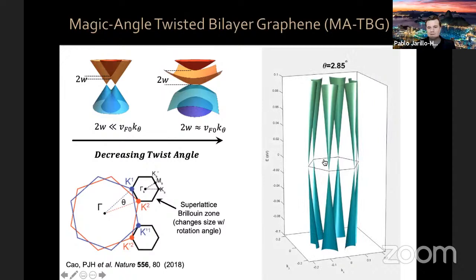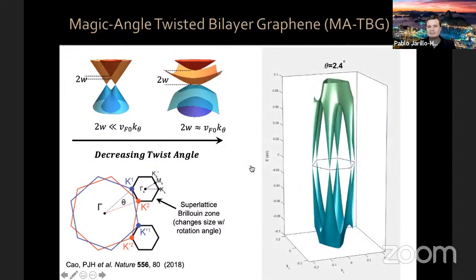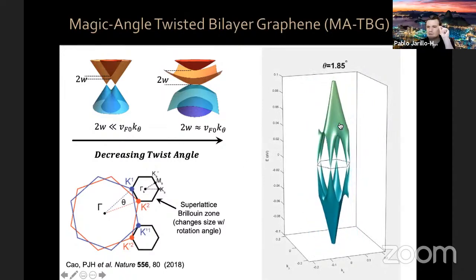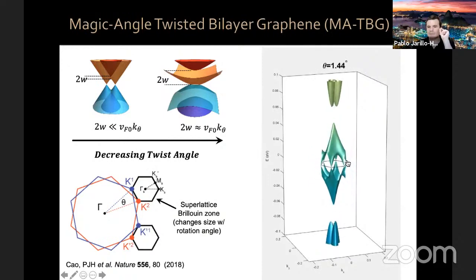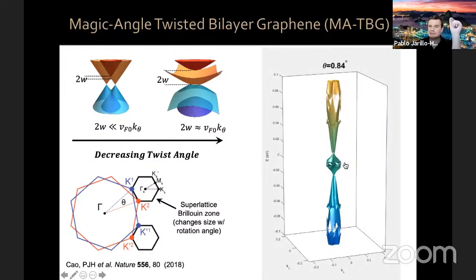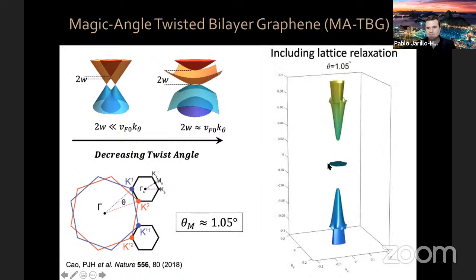So I'm going to run it again. As you can see, there is a particular sort of singular behavior. The band becomes extremely flat at 1.1 degrees, and it's less flat at 1.3 and at 0.8 degrees. So you can see this is a very flat band. This snapshot is for 1.05 degrees.